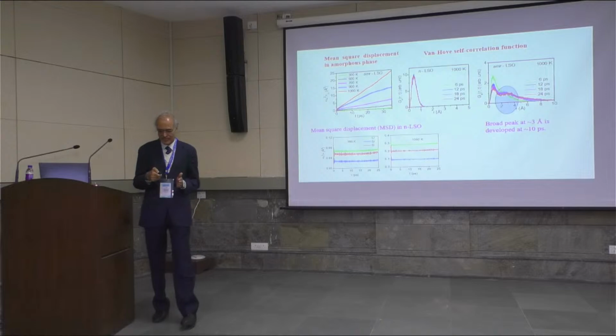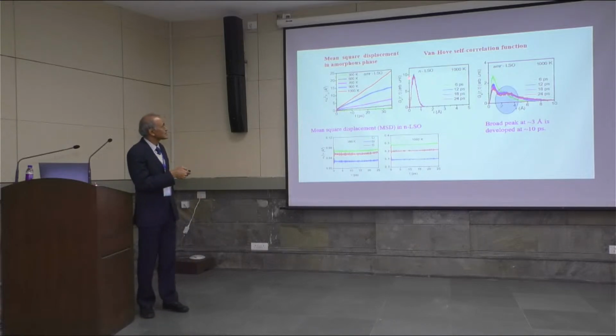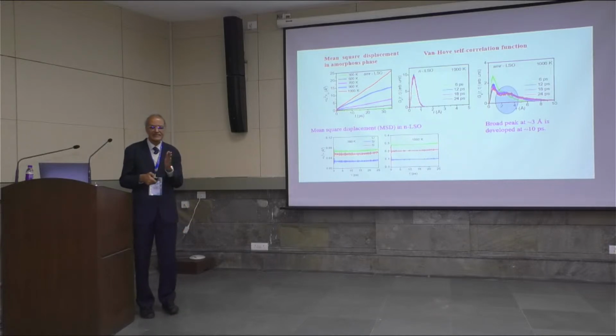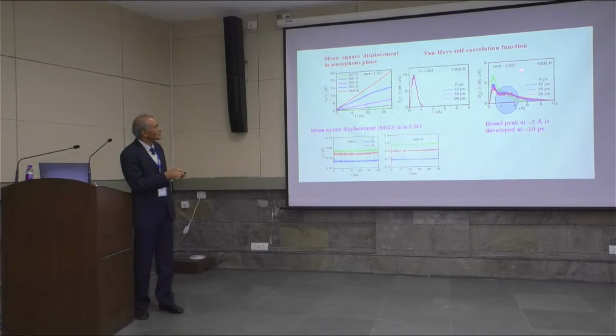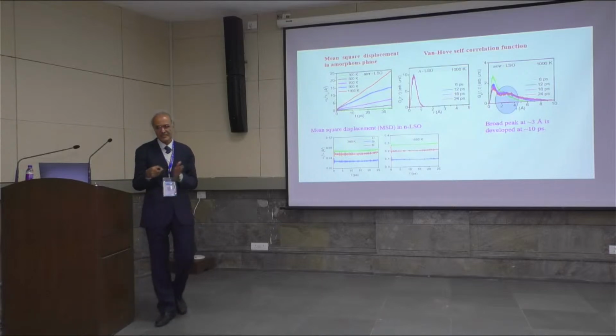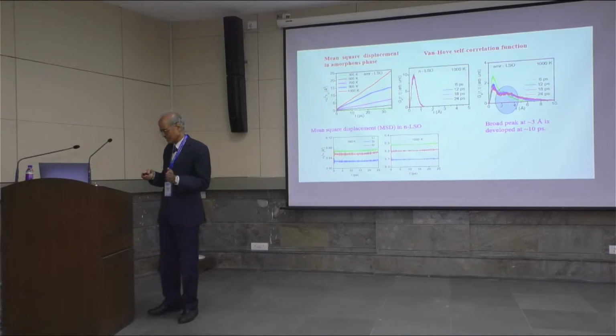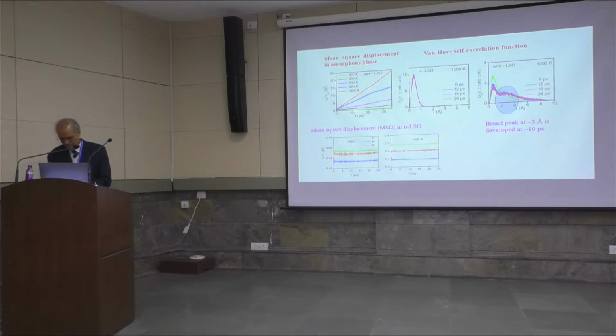Okay. So if you calculate that, in a crystalline material, what you find is that there is just one peak, typically, let's say, half an angstrom, and this is related to just the mean square displacement, the phonon kind of vibration. However, in this amorphous structure where there is diffusion, the self-correlation function first develops a second peak and then further broadens and so on. So this indicates how, as a function of time, the atom is jumping from an initial site to another site. So that's how one can look at it.